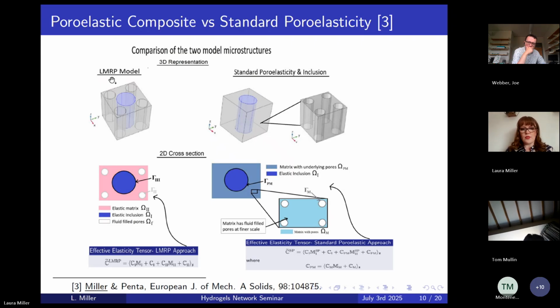So this is exactly what we wanted our new model to capture. Something where, when you look at it under the microscope, you can see minimum two distinct elastic phases and pores all at the same level. And that was new. Nobody had ever tried to propose a model where you could see the three things all at the one scale before.